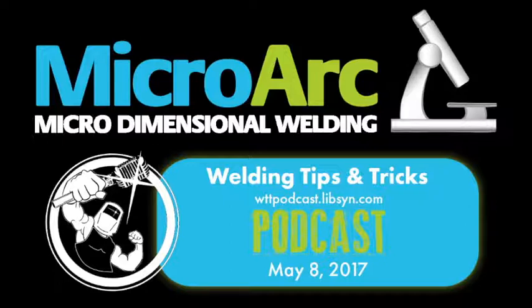Do you do any special prep for it, or just straight up tungsten grinder, or you just use a sander, or you polish it, or anything special there on the 1/16th electrode? Well, we hollow grind it by hand. There's all kinds of tungsten grinders out there, but I've never bought one. We hollow grind on a slight angle on a diamond wheel to a very, very sharp point, probably like a 25 degree angle or something like that. It's been 30 years, and I said, okay, that looks good. I don't even know, but it works for us. But I can't tell you exactly what angle it is.